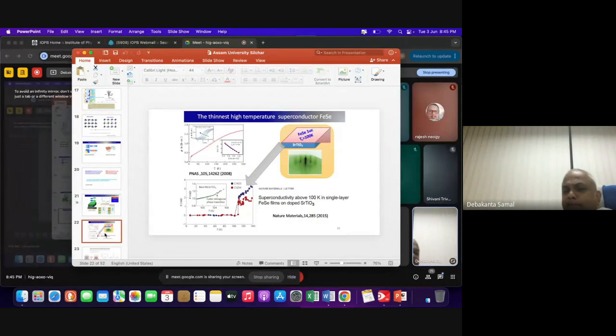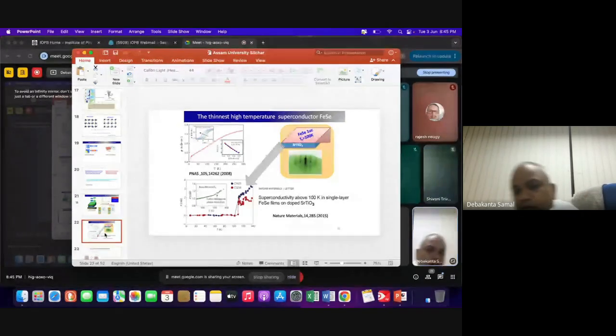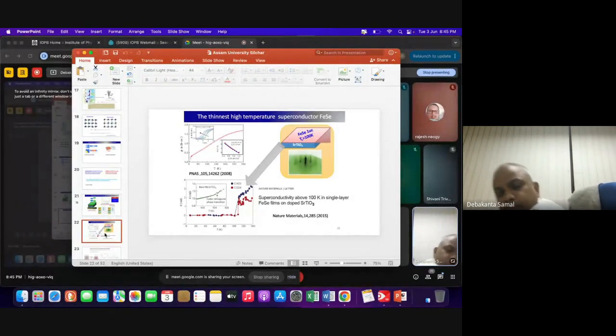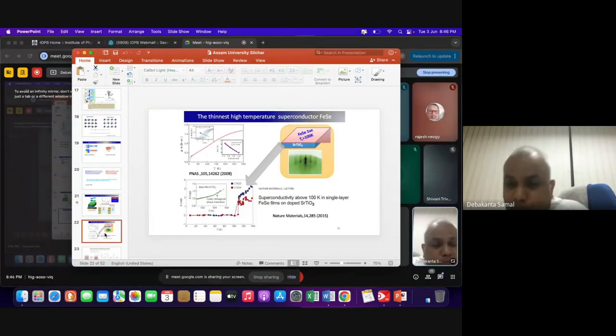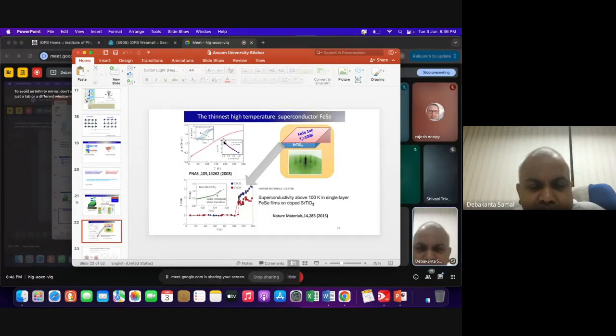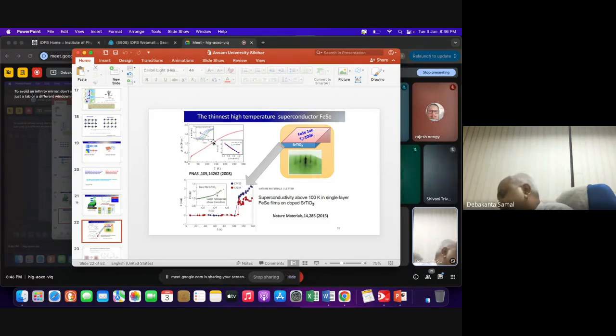There is another example I will bring. This was published, again in Nature, in 2015. I was working on superconductivity, but on high-Tc superconductivity in cuprates. This is a superconductor, iron selenide. Just remember that this is a superconductor in the bulk. And what is the TC? On the left-hand side, you see the TC is below 10 Kelvin. This is the superconducting transition temperature. This is resistance versus temperature. You see the resistance drops to 0 below 10 Kelvin.